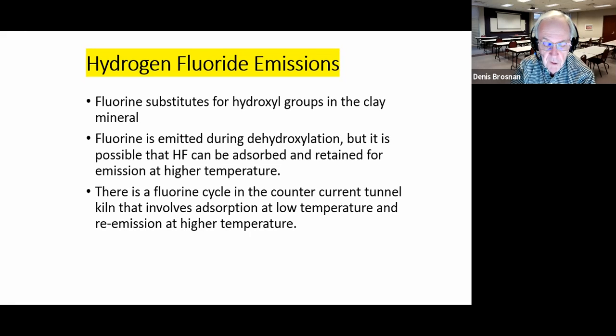So in ceramic manufacturing, if you're using a clay raw material, fluorine is part of the clay crystal structure, a very small part. It turns out that fluorine is about the same diameter and about the same charge as a hydroxyl ion, an OH. And therefore it substitutes for some hydroxyls, a few hydroxyls in the clay crystal structure, because fluorine was always in the environment when the clay was created.